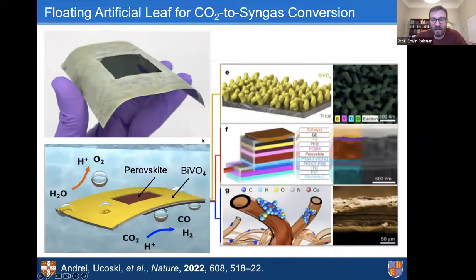To replace the conducting glass was a bit more tricky, and we used two different approaches here, or combined approaches. The first was, when it comes to the perovskite, we could just replace the glass by conducting PET or conducting plastic substrate. This was not an issue because we did not need very high temperature processing. However, for the anodic side with the bismuth vanadate, we need annealing. So in this case, plastic substrate was no option. So we ended up using an ultra thin titanium foil that we could then anneal. But the titanium foil is so thin that it's very light and you can also bend it. So ultimately, we could actually assemble these lightweight, flexible and bendable leaves.